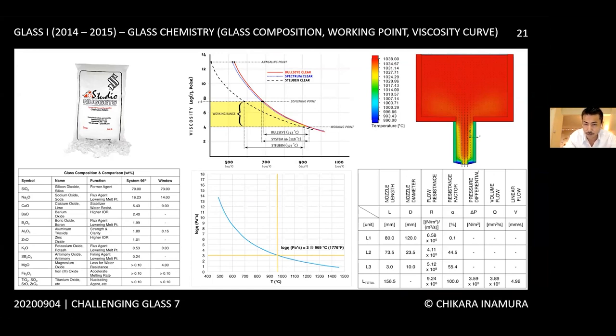Based on the glass composition, the viscosity curve and the glass transition temperature were determined using a VFT equation. And based on the viscosity curve, the target temperature at the nozzle was determined around 970°C to match the working point temperature of this glass. CFD analysis was conducted to account for the thermal loss, and thermal imaging was used to validate the spot temperatures. The system is gravity-based, and the flow rate of molten glass is determined based on the head pressure in the reservoir and the flow resistance in the reservoir nozzle assembly.